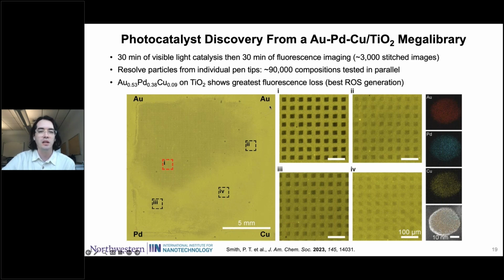So we made a library of gold, palladium, copper nanoparticles on a titania surface. And so we're looking at 90,000 compositions. You shine light on it with the rhodamine fluorophore as a coating, and then image the entire library here. And so you can then zoom in on regions of interest and compare the relative loss in fluorescence intensity. So we can see in this panel 1, it's much darker squares, so greater decay of fluorescence.